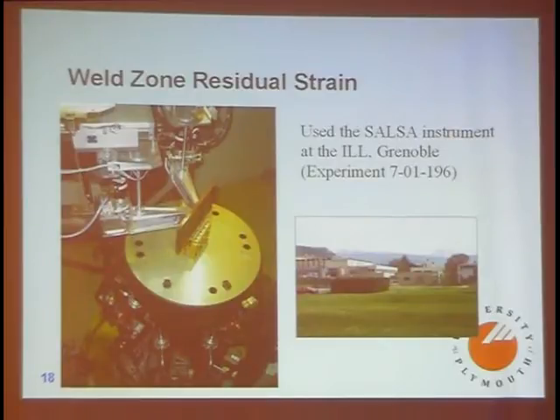And we've done that using the SALSA instrument at Grenoble, another fine alpine site. It's a vague picture, badly overexposed, of the Alps in the background, close to the nuclear reactor. And this is the hexapod table for the SALSA instrument with one of the weld plates in position, and you can measure the strains. And the point about this is you can measure strains actually through 50 millimeters of steel. And we actually did a 50 millimeter thick chunk of steel for Corus, just to see how residual strains varied from 12 millimeter plate and 8 millimeter plate.